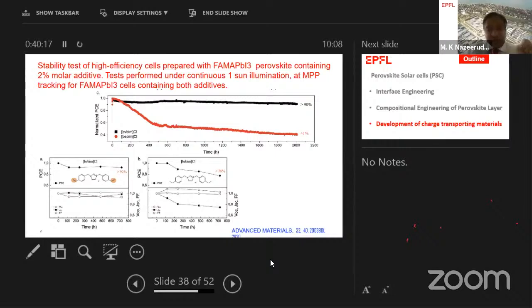So the difference in the stability data is a manifestation of this double bond, which is forming a self-assembled polymer layer within the perovskite composition. With this one, I completed my composition engineering of the perovskite layer, and for the remaining last 5 minutes, I will focus on the charge transport materials.